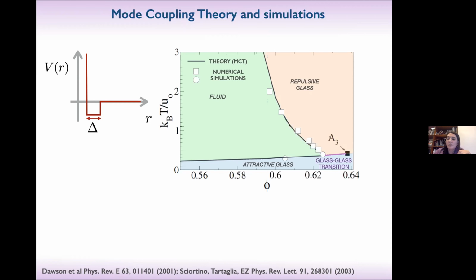And since this model is conceptually identical to the ones I showed you before, the schematic models, there is an A3 singularity here that happens in the glass, where the system goes from the attractive glass to the repulsive glass. Now we wanted to do simulation and to verify the existence of the higher order singularity. But as I told you before, you are forced to be out of equilibrium, and this could have dependence on the initial waiting time.